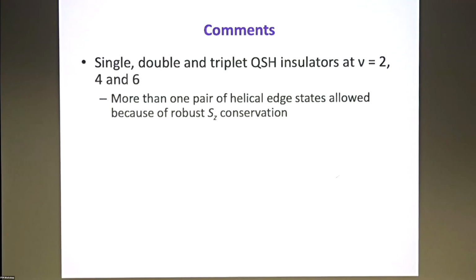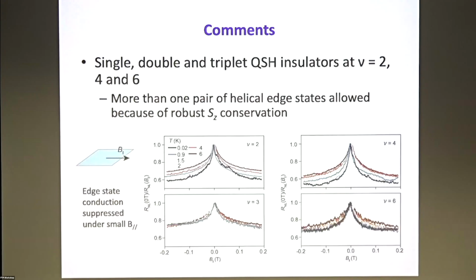Okay, just a few quick comments. Filling factors 2, 4, and 6 are single, double, and triple quantum spin Hall insulators. You may wonder why you can have an even number of helical edge state pairs on the edges. The reason is Sz conservation. This quantum spin Hall insulator is not protected by time reversal, but instead by Sz conservation. You can check that experimentally: if you apply an in-plane magnetic field, that will destroy the Sz conservation, and a small in-plane magnetic field can suppress the edge conductance quite a bit.